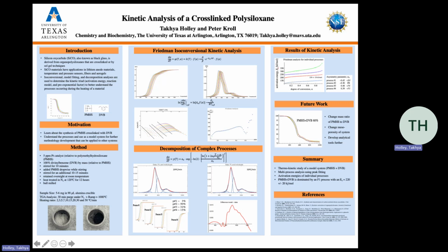In summary, we have done a thermokinetic study of the model system. We have done multi-process analysis using peak fitting, determined the activation energies for each one of the individual processes, and found that the dominating F1 process has an activation energy of 220 kilojoules per mole.